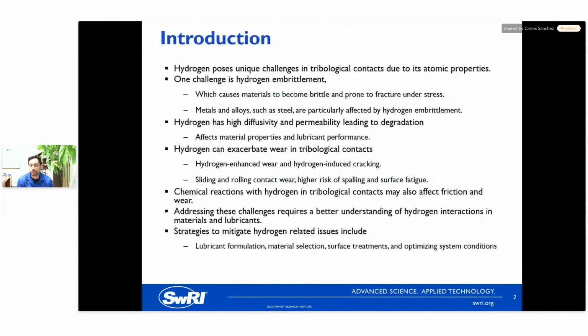All right, thank you. Anyway, introduction. Kind of what Mikro just talked about. Hydrogen poses unique challenges in tribological contacts for many reasons. One of them is that such a small atomic particle gets into your surfaces pretty readily. It can cause issues, especially in metallic surfaces, related to hydrogen embrittlement, where it gets into the crystal structure and causes fracture, premature wear, or stress cracking. It has very high diffusivity and permeability that leads to this type of degradation. It affects material properties and lubricant performance at various levels, depending on the material type and the severity with which the hydrogen is in that environment.